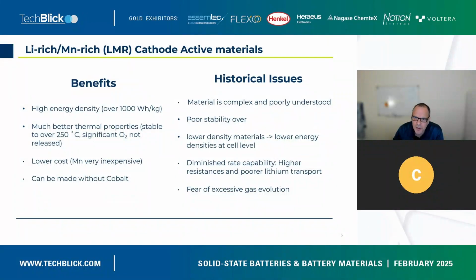And the other two things: diminished rate capability. It's a lower diffusivity material than the high nickel materials. And so oftentimes it's associated with being rate limited, and at usable rates like C/2, C/3 that you might want for an electric vehicle, it's thought to not be able to meet demand. And lastly is the fear, and sometimes evidence, of excessive gas evolution during use. And so if you can overcome these historical issues with a lithium-rich, manganese-rich system, you are maybe in a really good place.